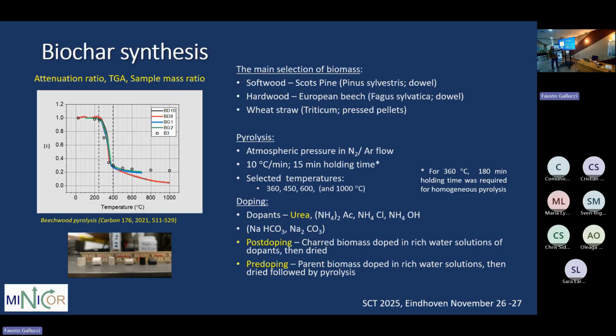Post-doping is produced by subjecting the char material to a rich water solution of dopants, and then it is dried. In pre-doping, we use the same procedure, but before the pyrolysis, and then we dry it. As you go up in temperature, you get biofuel first, and then later, where it is already carbonized, you produce these important gases, methane and hydrogen. This is the range of temperature where you obtain the biochar. The characteristics of biochar here and here are very different, particularly from the chemical aspects.